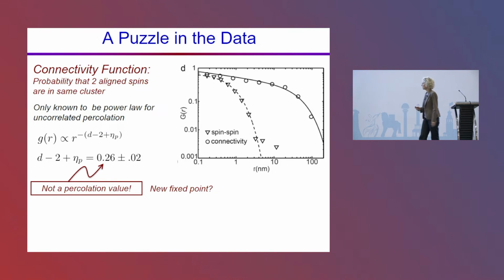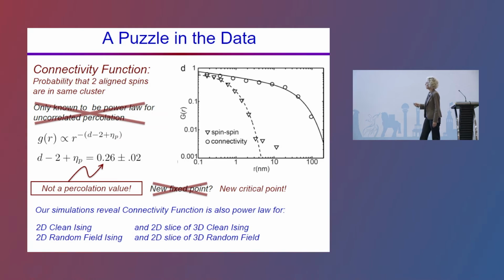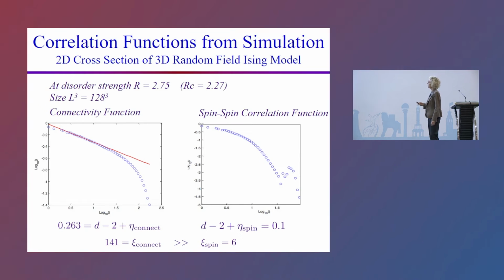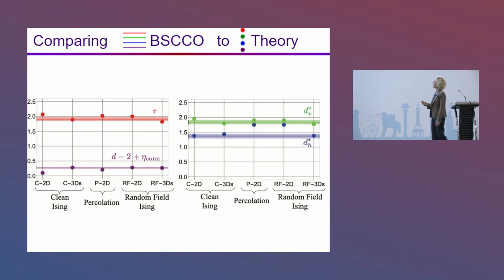And it turns out that, in fact, people hadn't studied this correlation function for the Ising model. So the connectivity correlation function, it turns out we calculated it in several different Ising models, and it also goes power law. It was actually already known from the 70s that it goes power law in the 2D clean Ising model, but we showed that it goes power law in the 2D random field Ising model and on free surfaces and on slices of the 3D models. So it's also critical in those. Sorry, it's also power law at all those Ising exponents. And I'll skip that analysis because of time constraints.